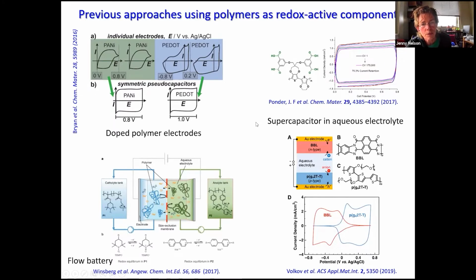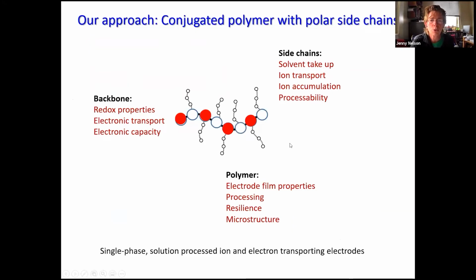Now our approach was really to see, can we do everything with the conjugated polymer? I don't mean all functions of the battery, but all functions of the electrode. So to not require any dopants, any binder or any additional conductive element, but rely on the different sides of the polymer to fulfill the different purposes. We would use the conjugated backbone for all the electronic properties, to define the redox properties, the transport properties, and the capacity. We would then use the side chains to interact with the electrolyte and the solvent.